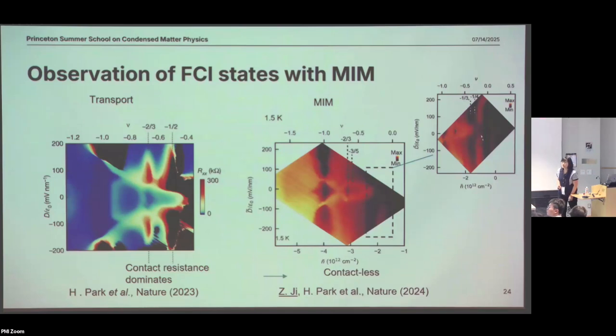Are the maps from an average over space, or from a particular spatial point? This is from a particular spatial point, but when you go around, it pretty much all looks like this, within some fluctuation of twist angle disorder and other disorders. And so that is a change from a contact resistance dominating case in this small filling factor region to a contactless type of measurement.